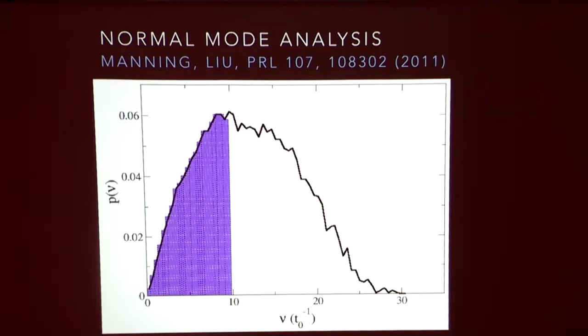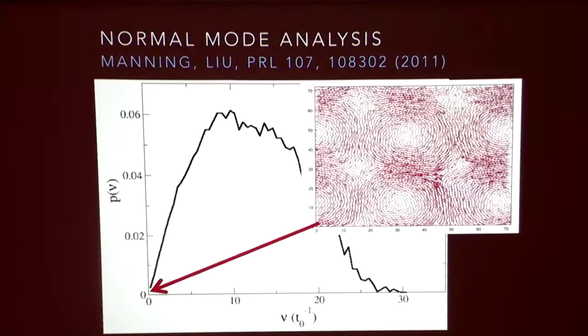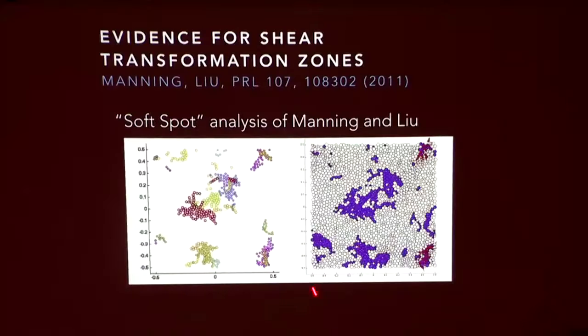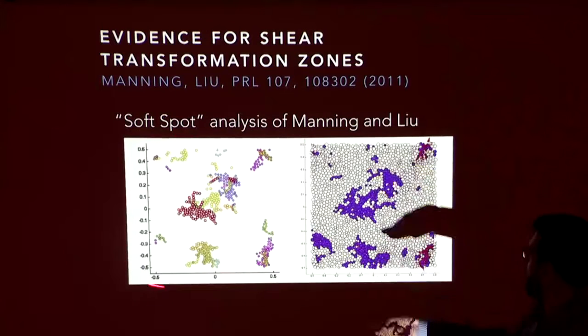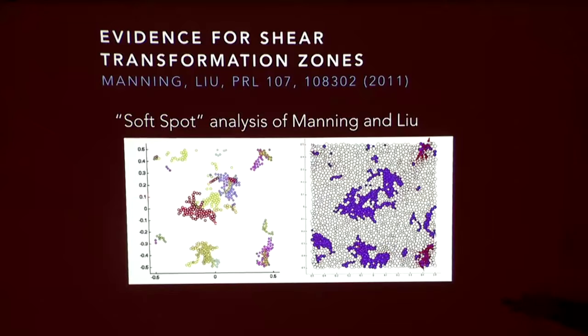So there are a few atoms that are maybe displacing more than the ones that are just engaged in the plane wave. Can we highlight those? They noticed that those tend to be activated more strongly in many of the low frequency modes. So when they did that, they could pull out some of the atoms in this two-dimensional system that participate disproportionately in the low frequency phonon modes, and then they would try to correlate those with where the system deformed when they sheared it at the boundary. They see a reasonable amount of correlation, but it's somewhat difficult to directly relate it.